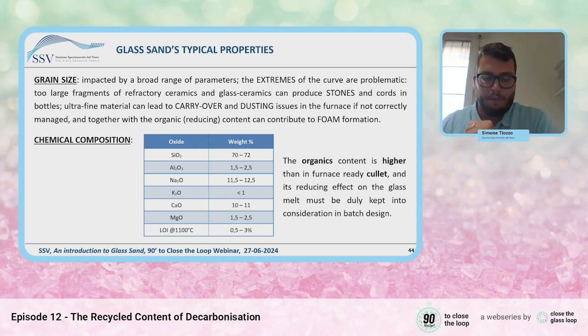Of course, there are some caveats, because you have to consider that this material may have a different capability of influencing the color or the redox state of the glass, and also there are final product specifications on glass articles, for example, for high-tier markets like cosmetics, perfumery, spirits, etc., where this secondary raw material is not very suitable, because the highest quality glass has even low furnace-ready cullet recycling rates. We have seen just some minutes before 20-40%, while on several other markets like the beer market we can get to 70, 80, 90% cullet recycling rate, with different colors, of course. So there are some caveats in the usage of this material.